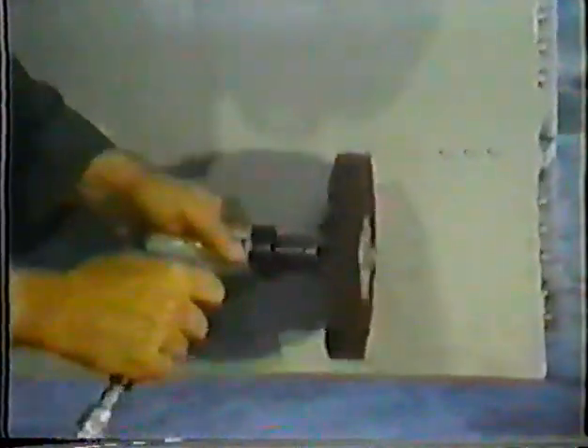With the paint removal procedure complete, your next objective is removal of the corrosion itself. First, hand scrub the corroded area with a dry, non-metallic brush. Then go over the area with a handheld abrasive mat, MIL-A-9962. Then hand rub the area with an aluminum oxide abrasive cloth of the appropriate grit. If the corrosion persists, go over the corroded area with a flat brush.